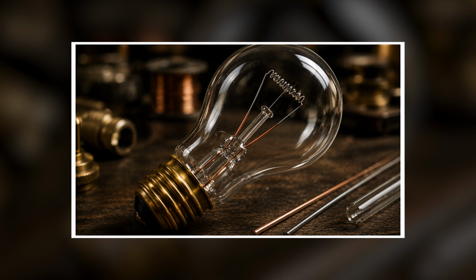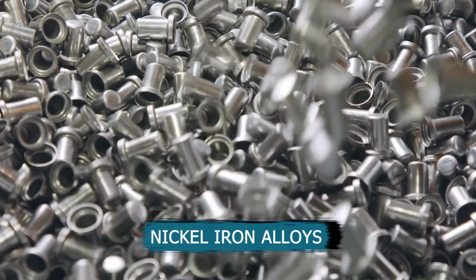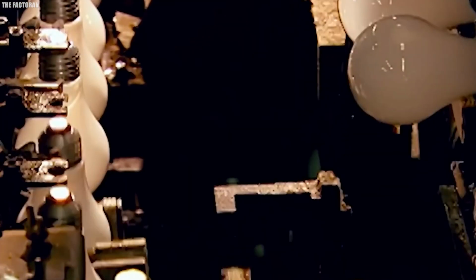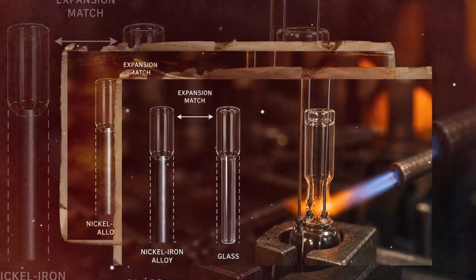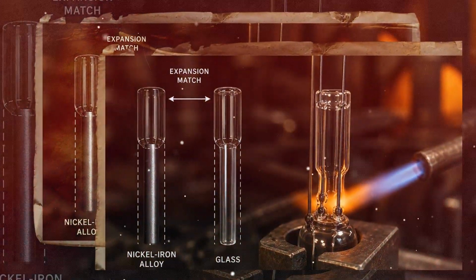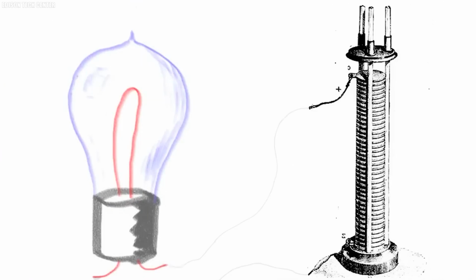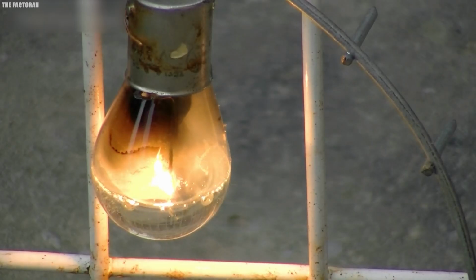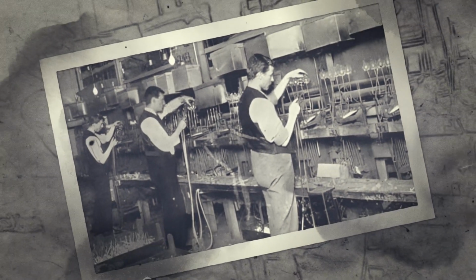Lead-in wires, the conductors carrying electrical current from the base contacts to the filament, were made from copper or nickel-iron alloys selected for their conductivity and thermal expansion compatibility with the glass stem they would be sealed into. Nickel-iron alloys were particularly valued because their expansion coefficient closely matched that of the glass used for stems, reducing mechanical stress at the seal during repeated heating and cooling cycles. The glass envelope was produced from a carefully formulated lime soda glass composition chosen to balance workability at furnace temperatures accessible to 1910s equipment with sufficient thermal and mechanical resistance for lamp service conditions.